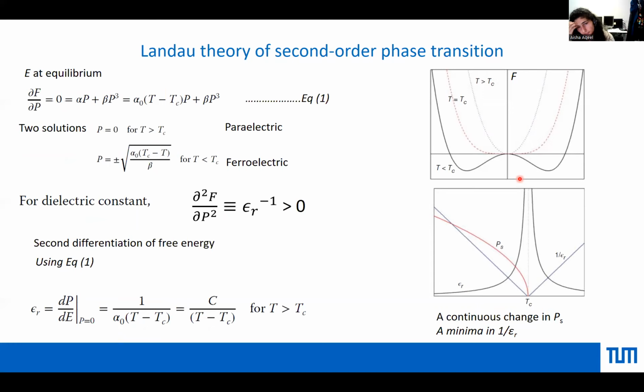If you take the second derivative of free energy, in this case it will be the dielectric constant. So if you take the second derivative of the first equation, you will just end up with this one. This constant alpha is a function of temperature. So this situation is just that the inverse of the dielectric constant changes linearly above Tc.